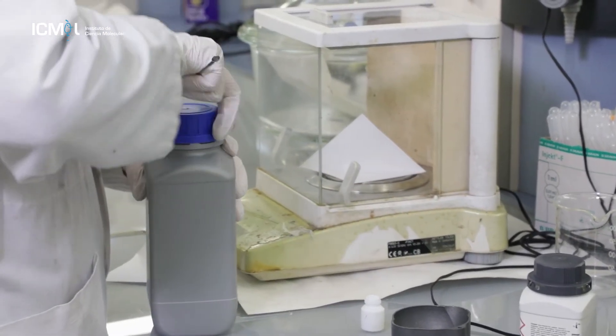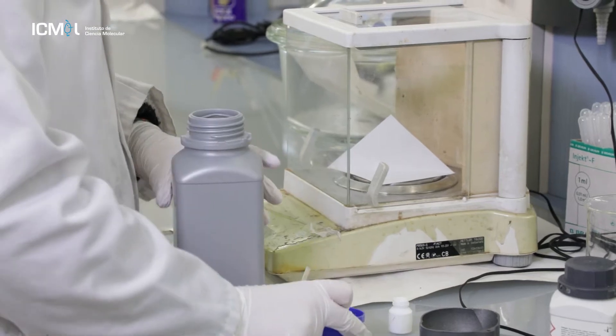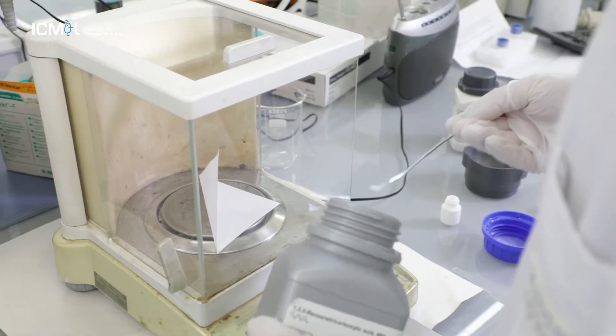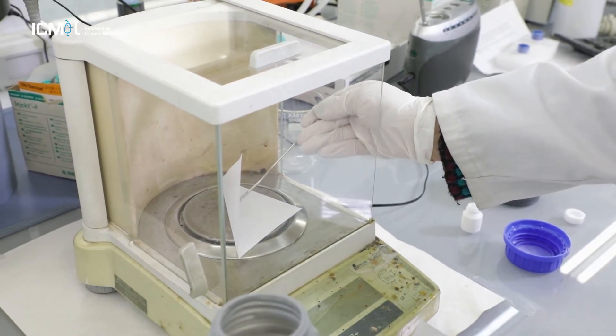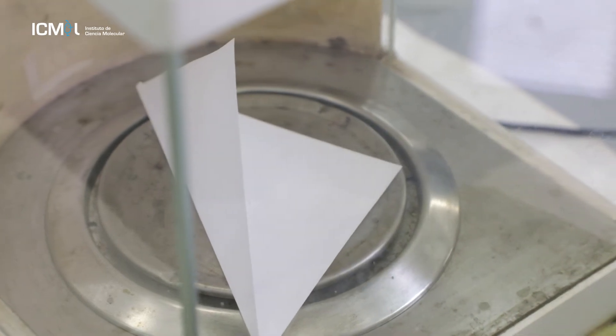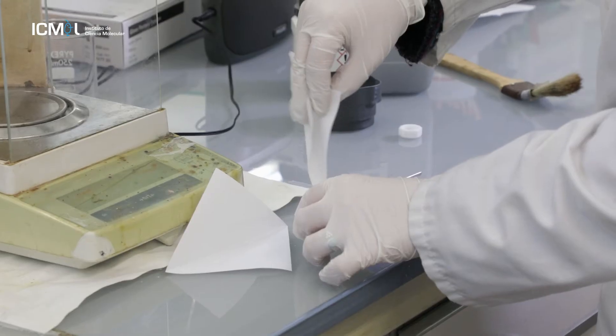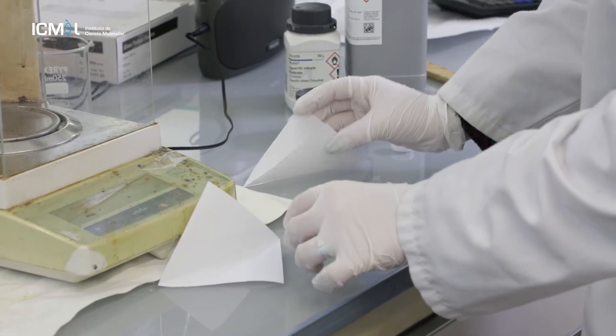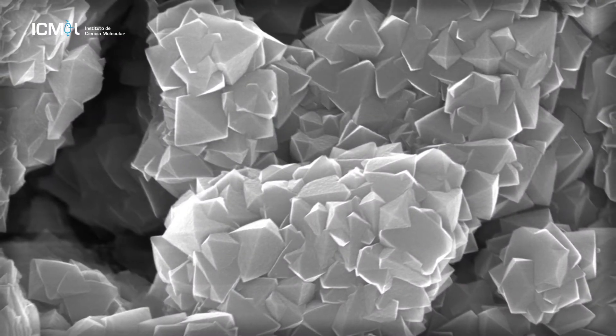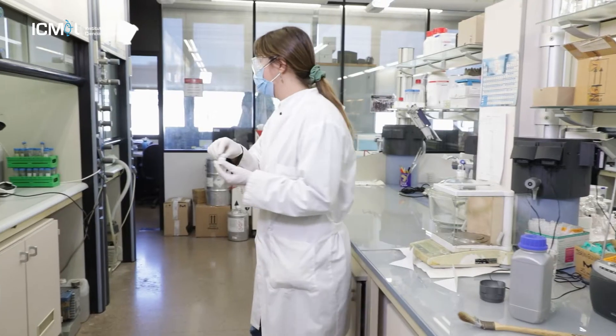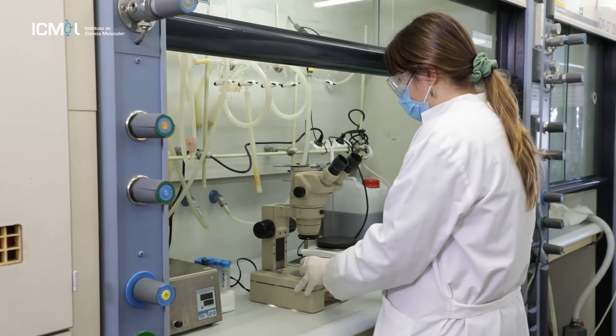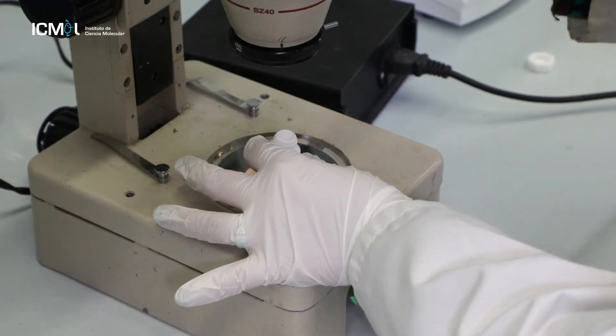So this can be done the classical way and we can use these small Teflon reactors for doing the synthesis of MOFs. With these we typically weigh the different components manually, that would be the inorganic salt, the organic linker, solvent and so on, load the reactors, mix them, and then heat them at controlled time and temperatures. Then we can open the reactor and analyze the product that is formed one by one. This is obviously hard work and certainly not the most effective way to explore the vast chemical space available when trying to synthesize MOFs.